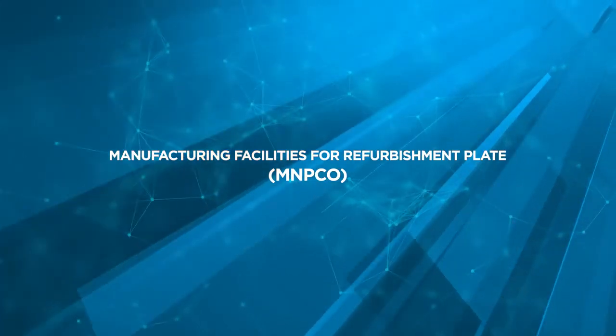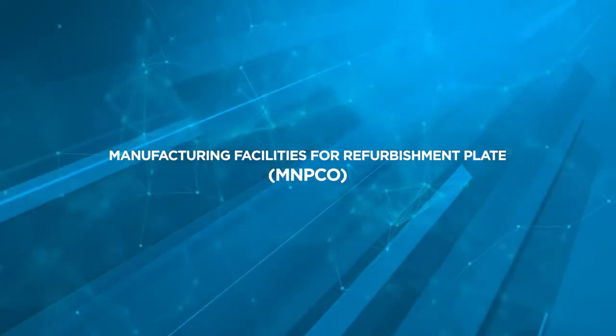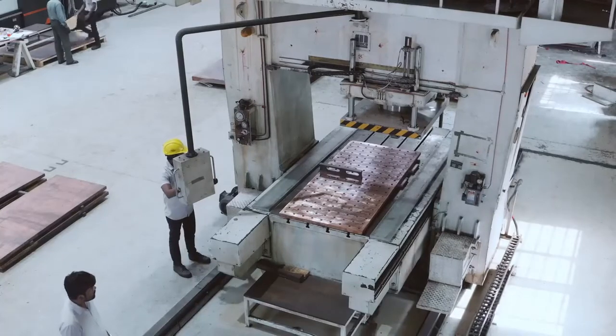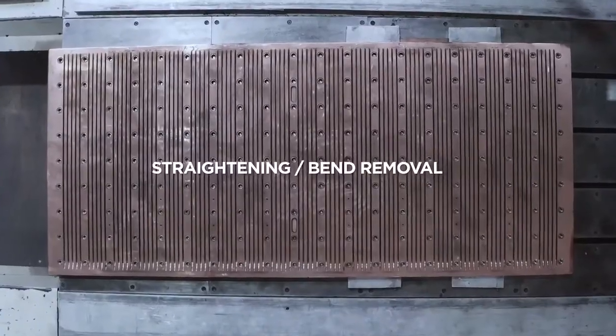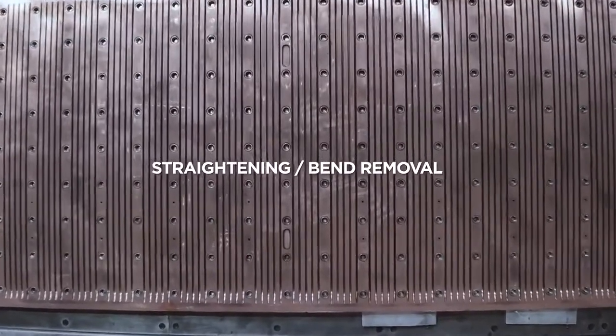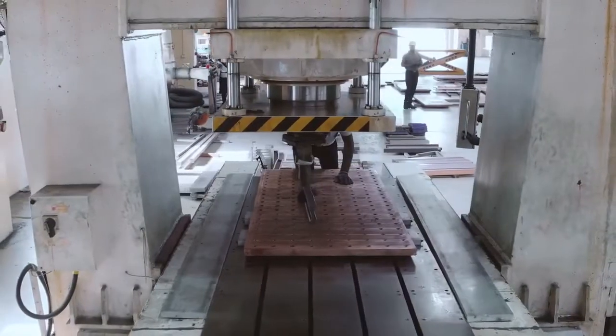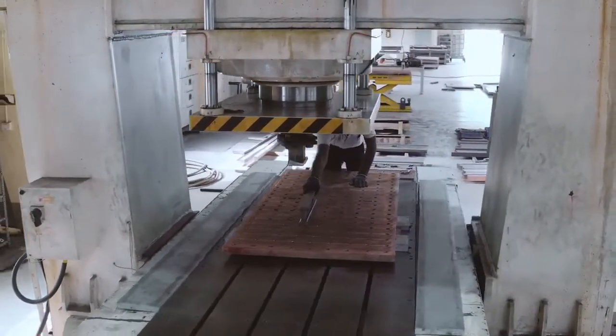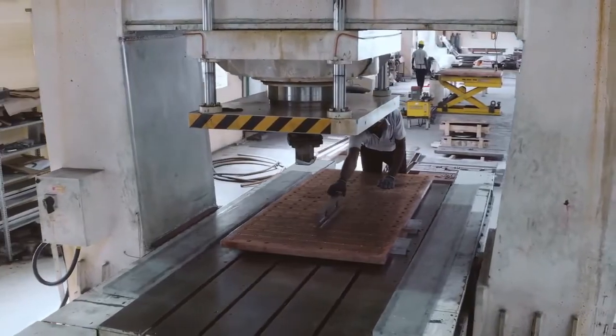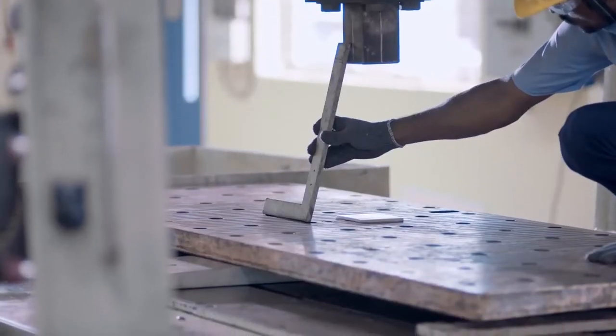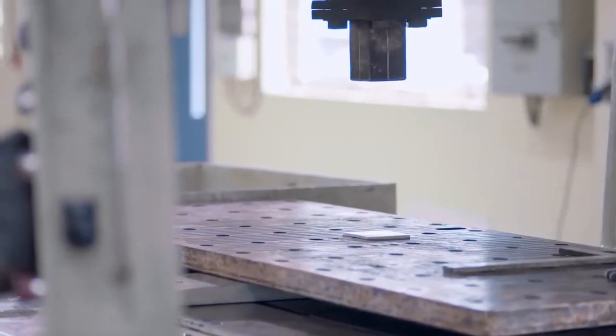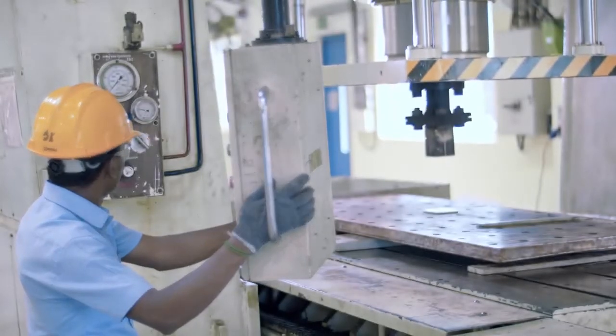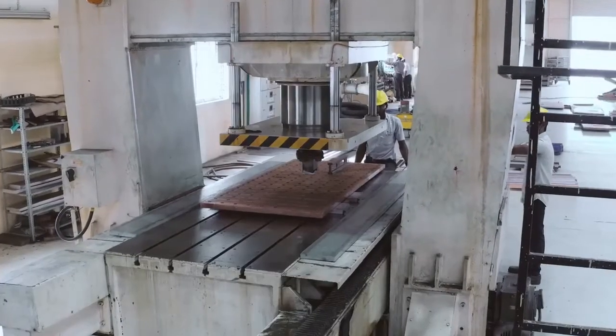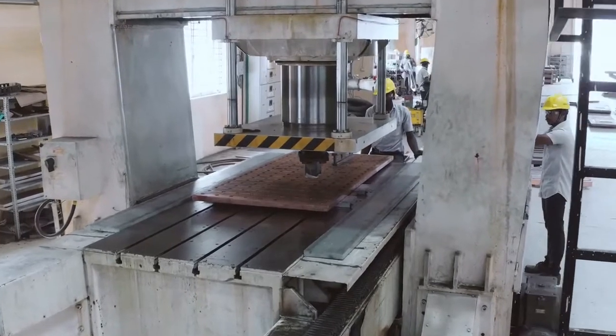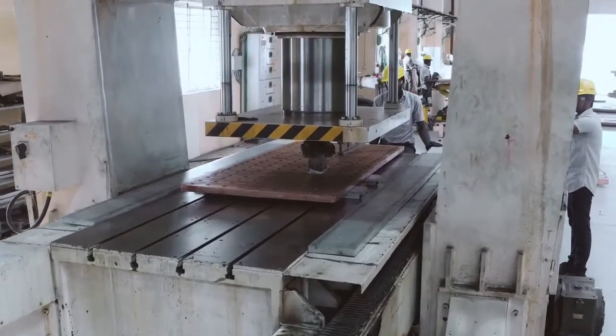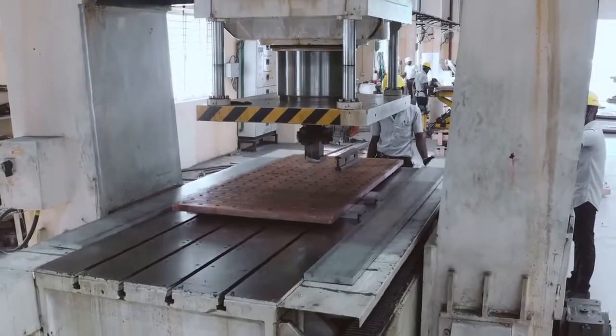Manufacturing facilities for refurbishment plate, MNPCO. The used mold plates have significant bend in the width and length in addition to the wear and surface damages. The mold plates to be refurbished are first thoroughly cleaned to remove the scales. The bend in both X and Y axis is inspected and recorded. The plates are then straightened in both axes on our hydraulic press.